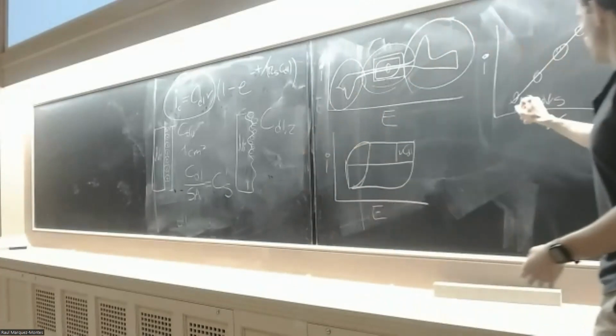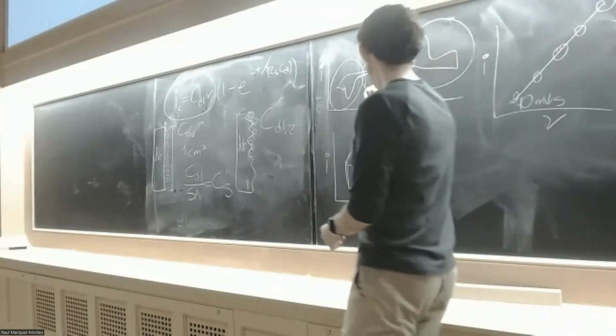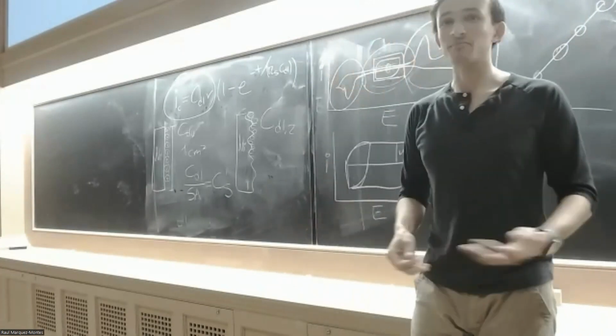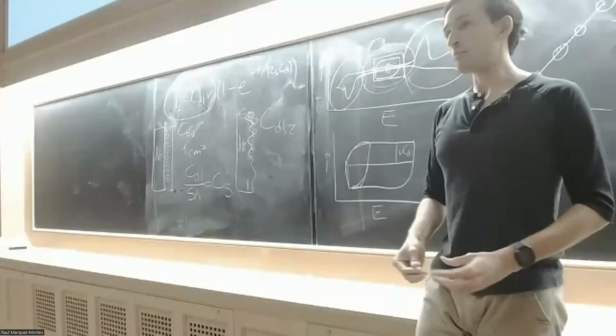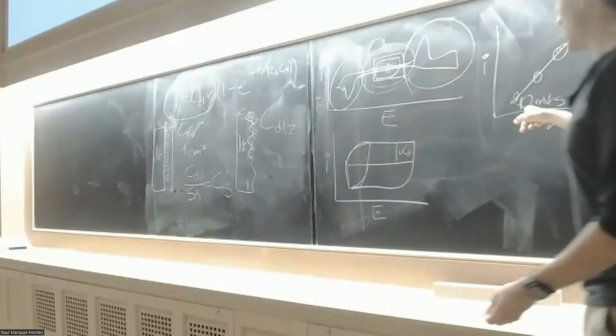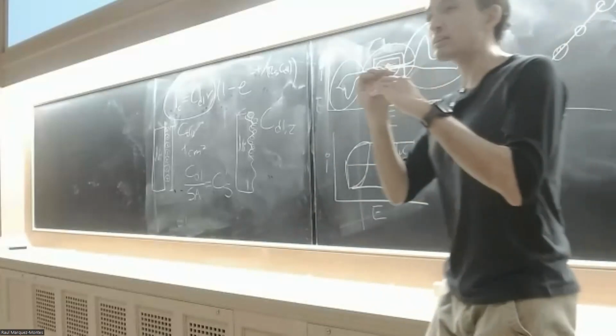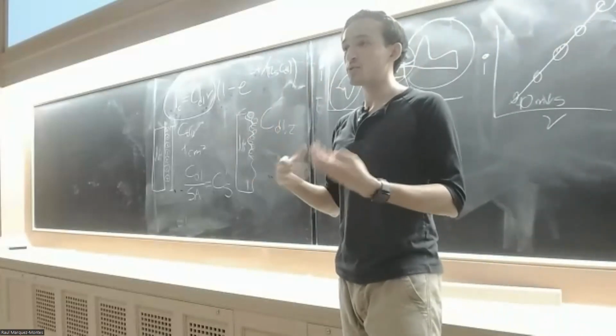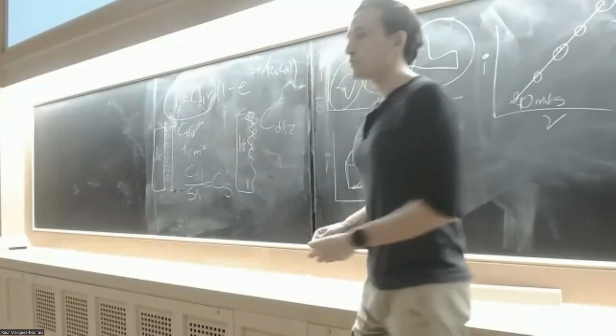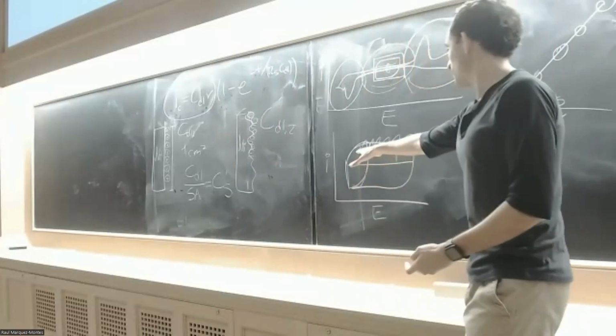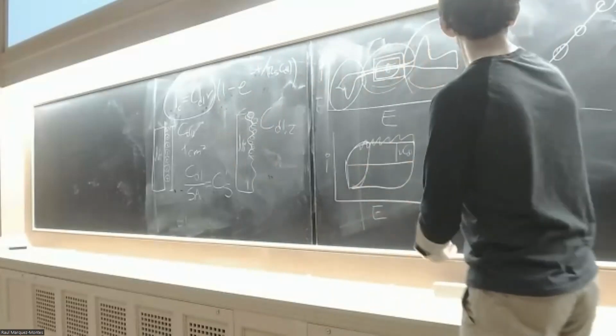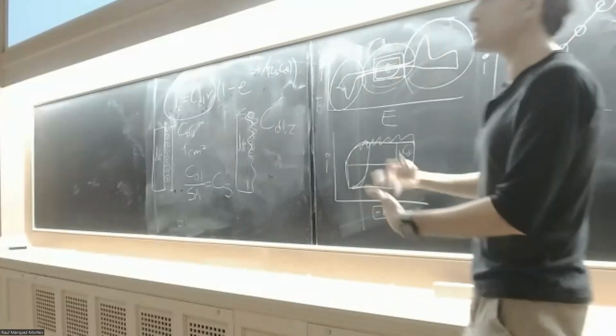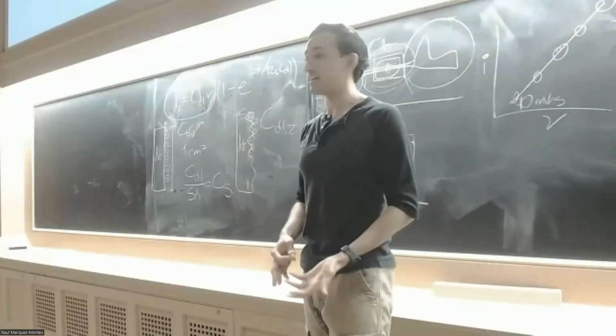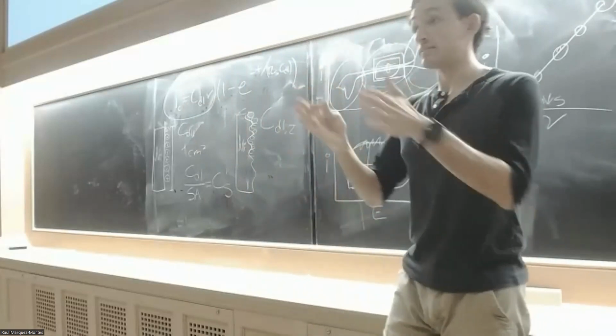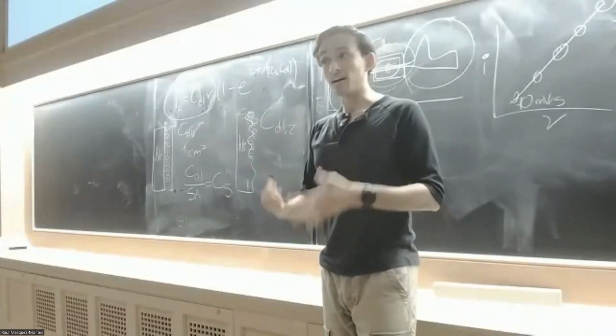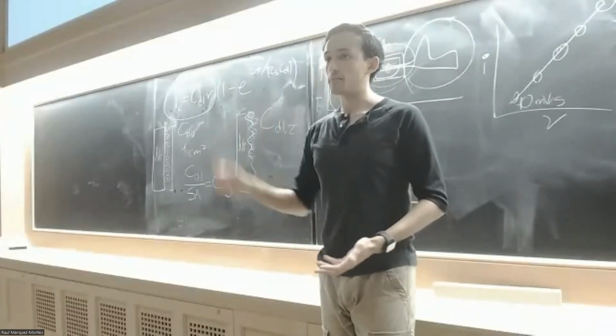Because when you have a very small scan rate, you will have a very tiny current, like nanoamps or like 5 microamps. And some people may say, oh yeah, but it's flat. But yeah, you're just scanning 10 millivolts per second. So it's really, really small. Sometimes you will have noise, so you will see something like this, and you won't be able to see this plateau clearly. So if you increase the scan rate up to 1 volt per second, you should be able to see a clear plateau. If you don't see it, either the potential window is not in the right position, or the material maybe is not conductive, so that's why you're unable to see this shape. Okay.